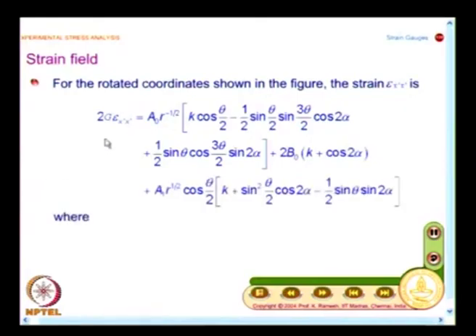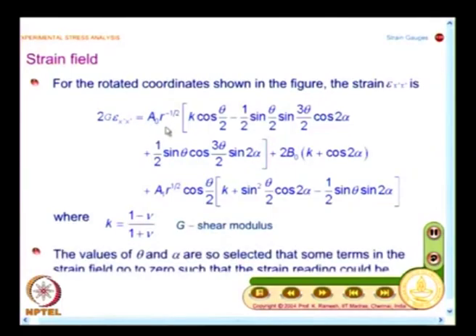So, what I have here is 2 g epsilon x prime equal to A naught r power minus 1 by 2 multiplied by kappa cos theta by 2 minus 1 by 2 sin theta sin 3 theta by 2 into cos 2 alpha plus 1 by 2 sin theta cos 3 theta by 2 sin 2 alpha plus 2 B naught, with kappa plus cos 2 alpha. So, now you have a clue how to find out alpha. This should be minus kappa. If I have this as minus kappa, then this term will go to 0. So, find out alpha and then find out theta, that is how you play with the equations.